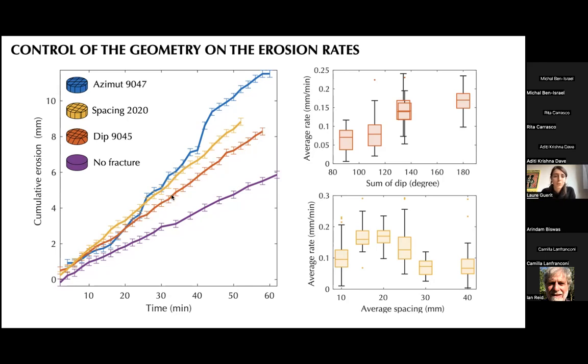I show you the average erosion rate. So this is the slope of this curve here with respect to the dip. Here I simply take the dip of the two families and sum it. And you can clearly see that the more vertical the fractures, the higher the erosion rate. And this increase is, let's say, a factor of 4. So we clearly document the impact of the vertical orientation of the fractures with respect to the flow.